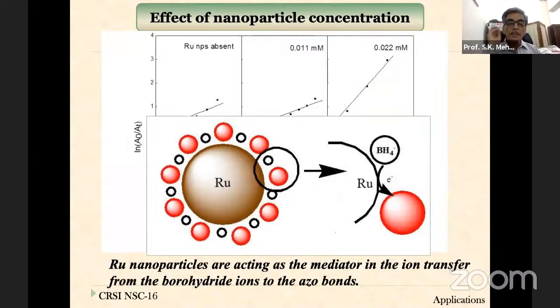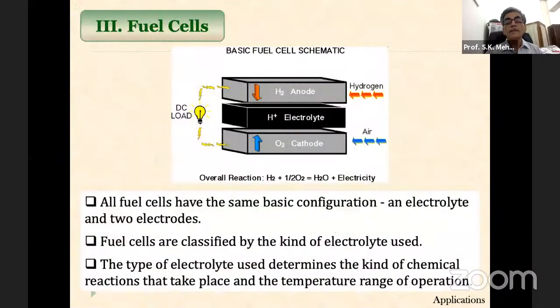So this was basically the mechanism which was proposed, that ruthenium nanoparticles are acting as a mediator in the ion transfer from the borohydride ion to the azo bonds. So this was the reason how this degradation takes place.